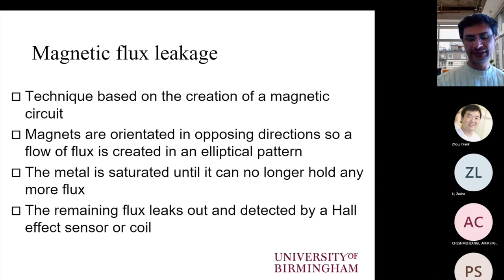So if we have a defect of appropriate orientation and appropriate severity, then flux will leak, and hopefully this should be detected by the sensors that are incorporated together with the magnets that generate the magnetic circuit. This can be done either using coils in the most simple type of sensor, or more often in modern equipment using Hall probes. Of course, we can use other sensing instruments such as GMR, but at the moment, commercial systems tend to include Hall probes instead.